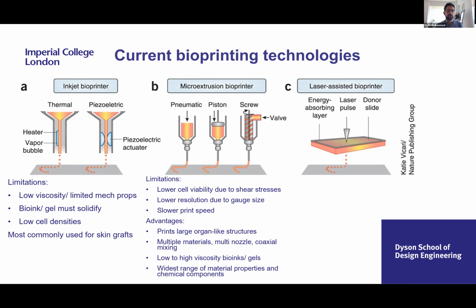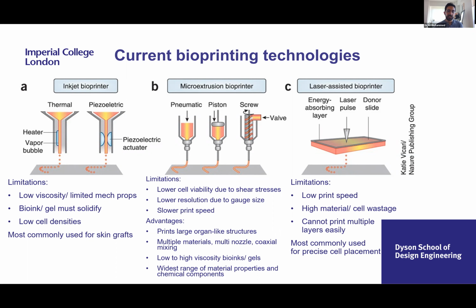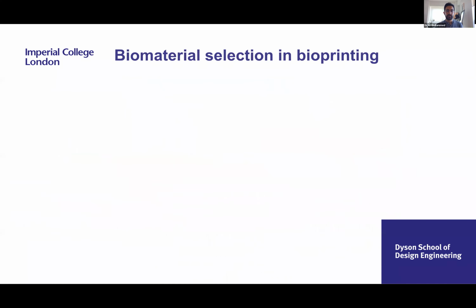You've got multi-nozzle and coaxial mixing, so you can have a more complex material. Low to high viscosity bio-inks can be used, and gels that are already set. Some limitations of laser-assisted bioprinting are a very low print speed, high material and cell wastage as you only deposit a small amount from a large vat, and it cannot print multiple layers very easily. So this is really just limited to precise cell placement.